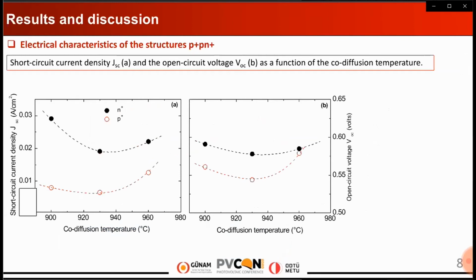Let us now show the effect of co-diffusion temperature on the electrical characteristics of the prepared bifacial structures. We present here the variation of short circuit current density on the left and the open circuit voltage VOC on the right as a function of the co-diffusion temperature. One can clearly see that the emitter N plus yields higher current density with VOC more important compared to boron BSF.